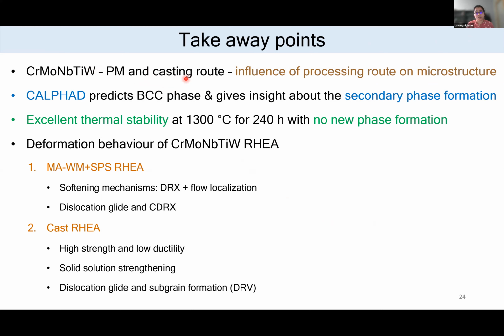So to summarize, the takeaways from this talk are that this composition, when we try to synthesize through different routes, really shows how the processing route can affect your microstructure. And also we can validate our experimentally observed phases with CALPHAD, which is a unique tool that gives insight about the plausible secondary phase formation. The alloy also has an excellent thermal stability, wherein no new phase was formed. In the deformation behavior of this alloy, the MA-SPS alloy showed dynamic recrystallization and flow localization as a softening mechanism. Whereas in the cast HEA, we have solid solution strengthening as the major strengthening factor, and dynamic recovery as the mechanism.